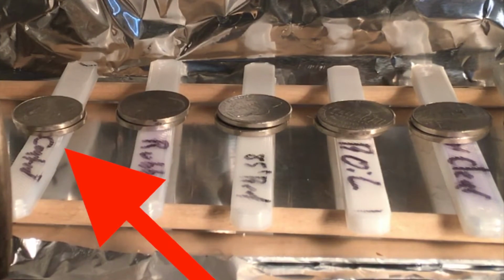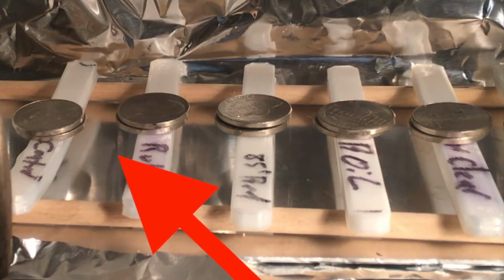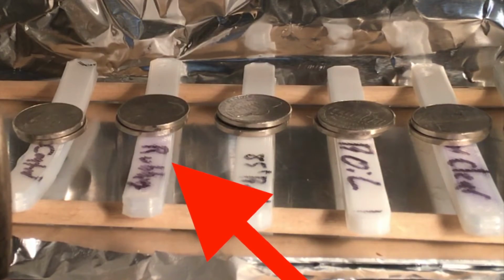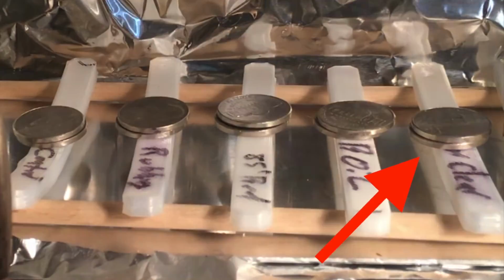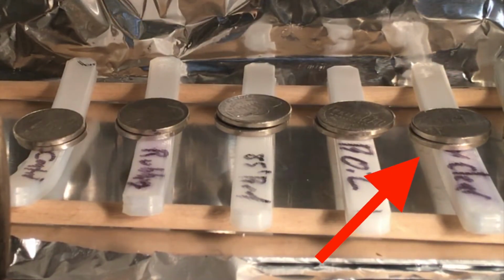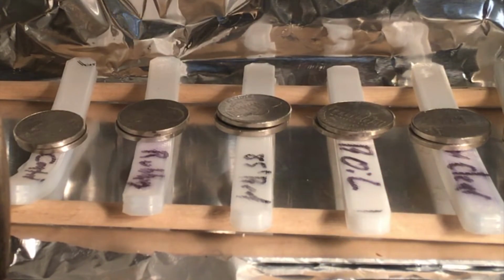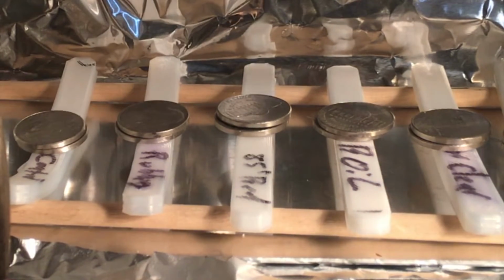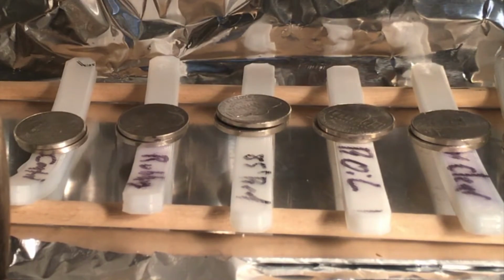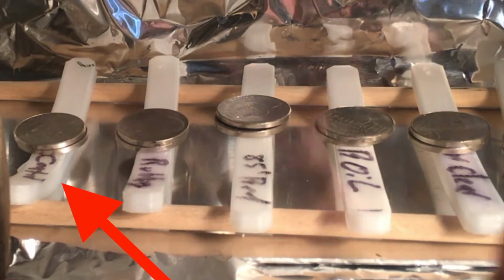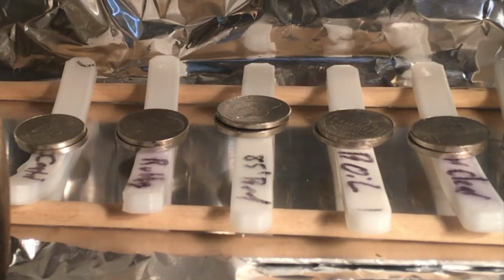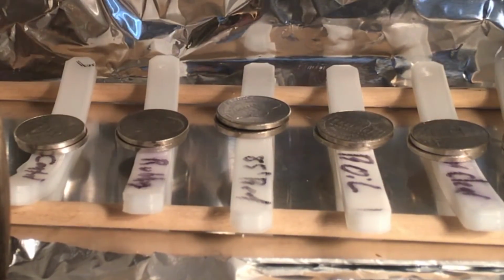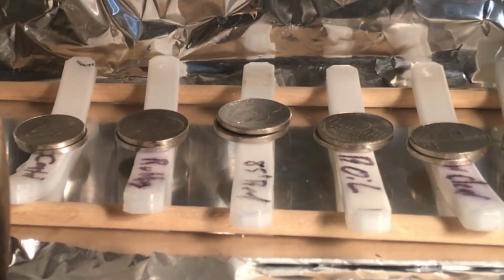Now you can see immediately the control starts to melt as I heat it up, followed by the rubbing alcohol, which seems to have a little bit better deflection, but not as much. Then that's followed by the Everclear that was soaked for an hour at room temperature. And then finally, as I fast forward more and turn the heat up, the control is practically liquid, but we get a little bit of movement here on the boiled piece and the piece that was annealed on the bed.